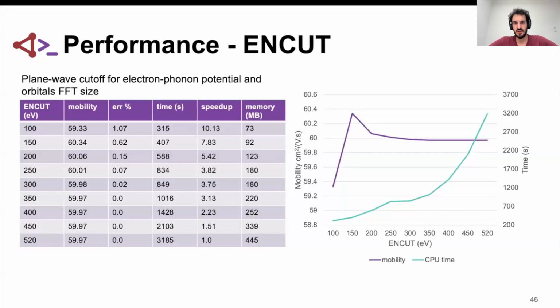One of the INCAR tags that impacts performance a lot is ENCUT, which determines the plane wave cutoff for the electron-phonon potential and the FFT size for the orbitals. In this table, I show different values of the cutoff and the final mobility we get after calculation, along with the error with respect to the value with the highest cutoff, the computational time, the speed up, and memory.